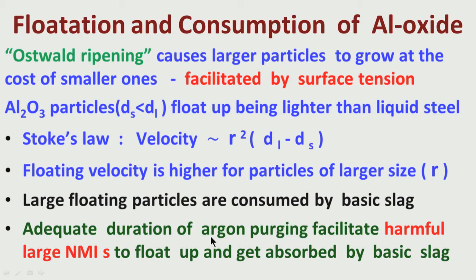So the duration of argon purging is very important. An adequate duration of argon purging, say about 15-20 minutes, is necessary to allow these particles to float up. These larger particles are harmful. So fortunately, if you give adequate time through argon purging in the ladle, these harmful large NMIs will float up and get absorbed by the basic slag.